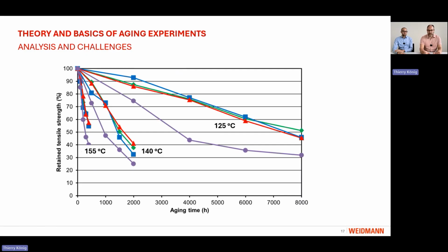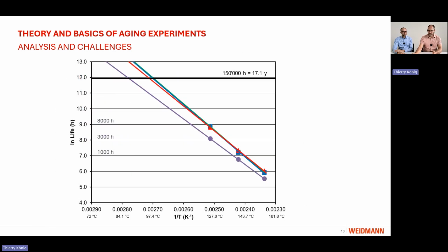These temperatures and the corresponding times are now put into this Arrhenius plot. And at the end, what we get, and what was also used by Arrhenius, is this linear plot here. So we have 3 different temperatures with corresponding times in a logarithmic scale, and we can extrapolate from this 8000 hours that we have used to a transformer lifetime, which was here chosen as 150,000 hours, or about 17 years. And you can go down then to the x-axis and see what temperature this means, which in this example is 98 degrees.